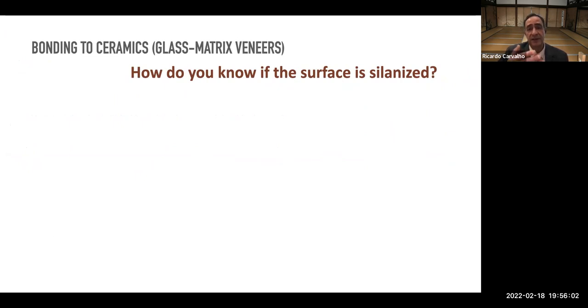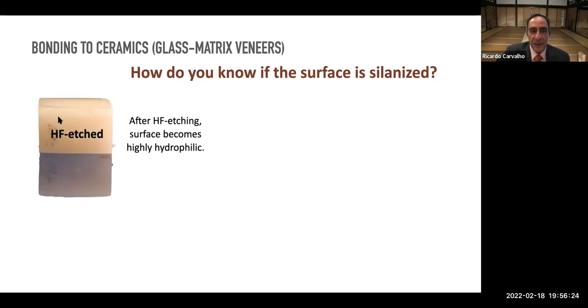But how do you know? Let's say the lab tells you, well, I send it to you already etched and silanized. And as I told you, if you just look at the ceramic surface, you cannot tell if it is silanized or not. So how do you know? There is a way to learn that. After etching, the surface usually becomes highly hydrophilic. It's probably hard for everybody to see here, but this is a block of ceramic that I etched with hydrofluoric acid. And then I dropped a drop of water on the surface. As you can see, the water spreads readily on the whole surface.